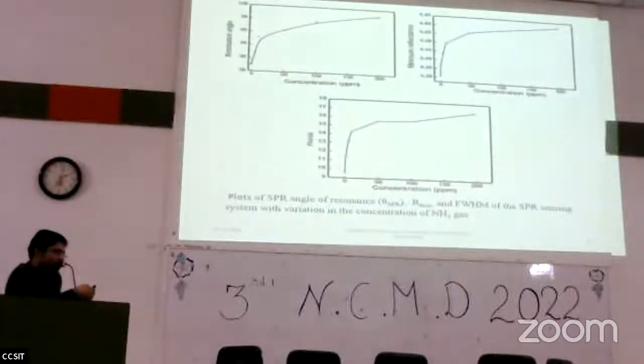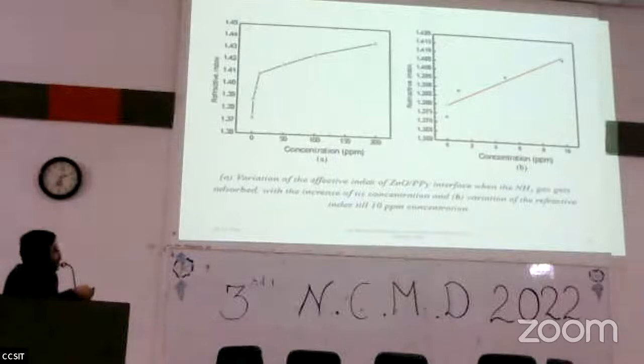Again, we plotted the three parameters: resonance angle variation with concentration, minimum reflectance with concentration, and full width at half maximum with concentration. Then the refractive index variation with concentration. We can see here that up to 10 ppm, which we have plotted separately, this variation of refractive index with concentration is linear. This justifies that we can use this composite as a sensing material. So this is our calibration curve.